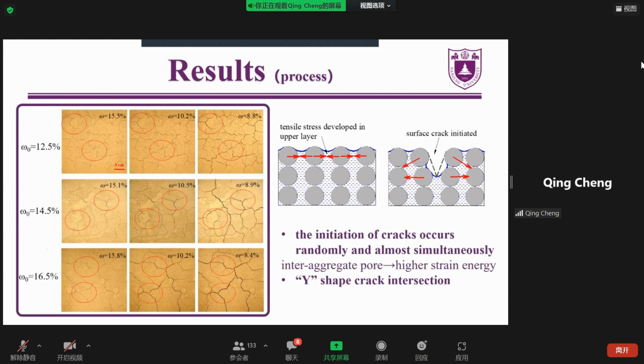And this slide shows the crack initiation and propagation of each soil sample. For the soil samples compacted on the dry side and at the optimal water content, we can find that the cracks initiate evenly on the soil surface and then widen gradually. The initiation of the cracks occurs randomly and almost at the same time on the surface of the soil sample. This is because the cracks usually initiate at the surface defects where shrinkage distortion or stress concentration occurs.